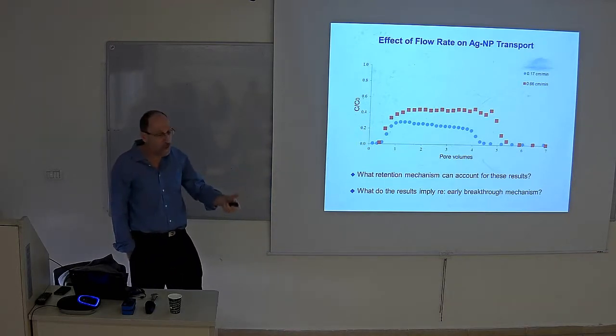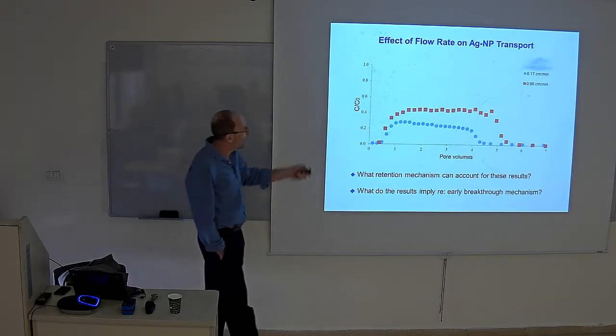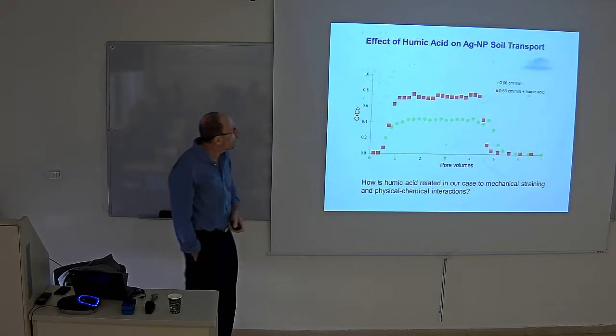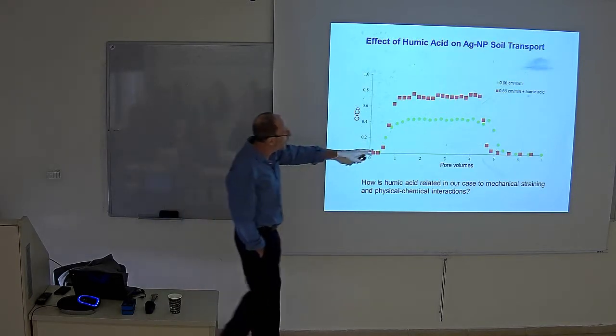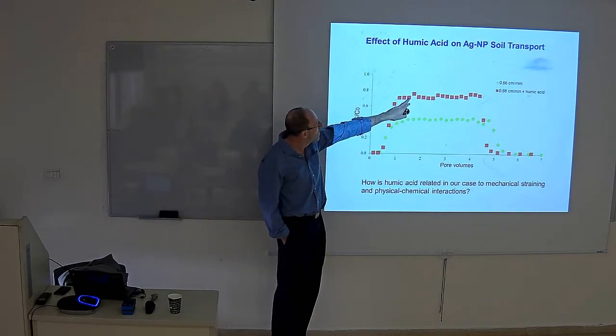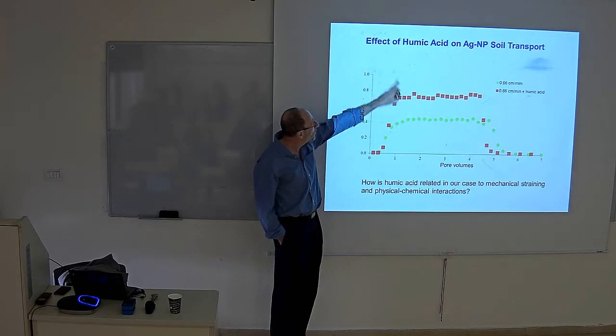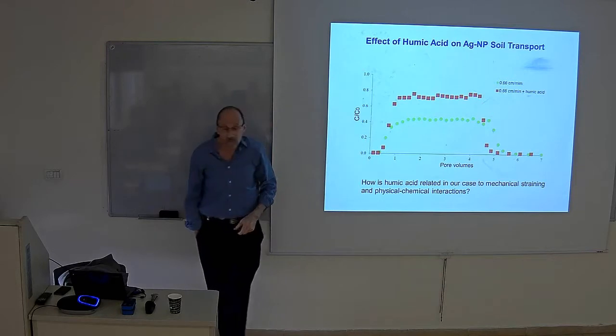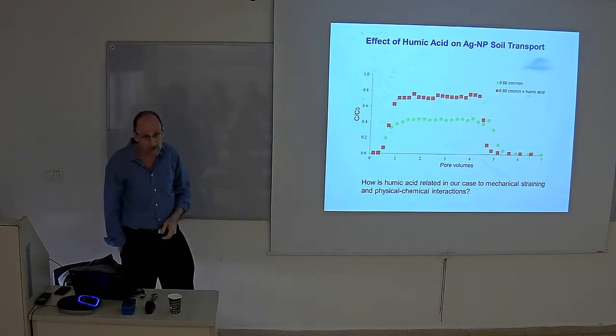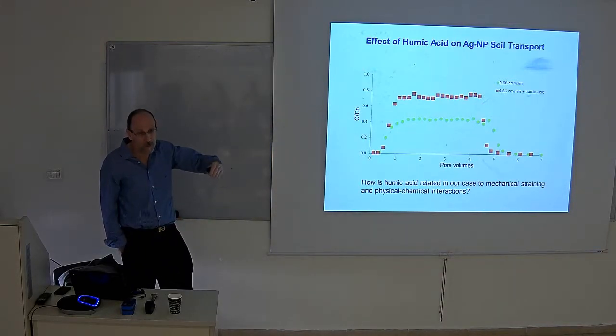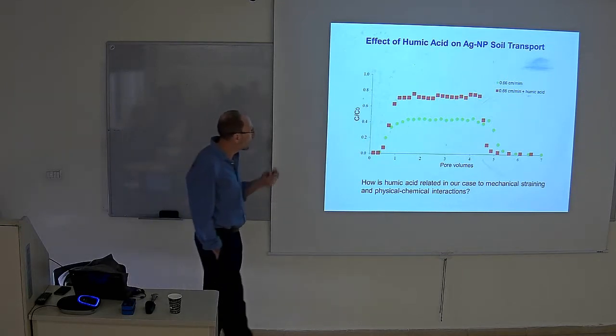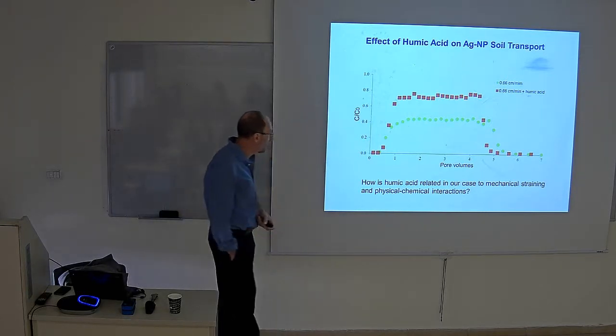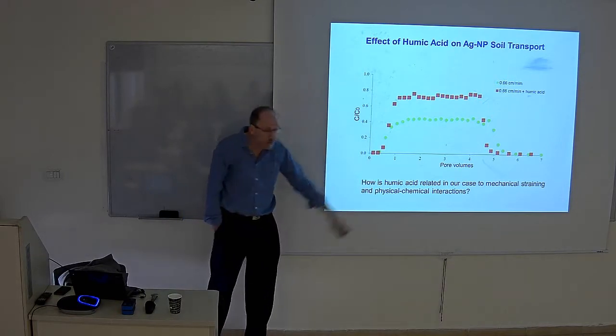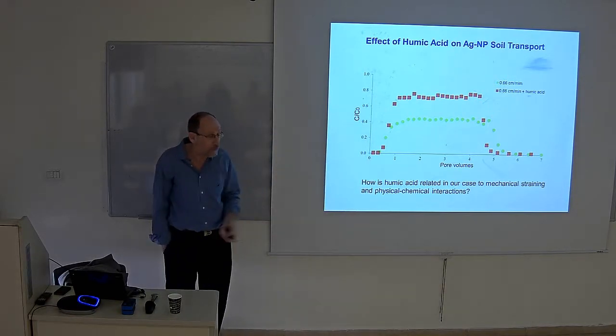So we've got humic acid, we've got the surface effects, we've got the flow rate. You can play also with the effect, again, this is showing the effect of humic acid in the column. Even with the humic acid, it's more mobile, and you still don't get 100% recovery, 80% as opposed to 40-50% without the humic acid. Lower the flow rate, and you get even less coming out. So this is, again, just to try to understand the basic phenomena. Again, how exactly humic acid interacts, that's still an open question then.